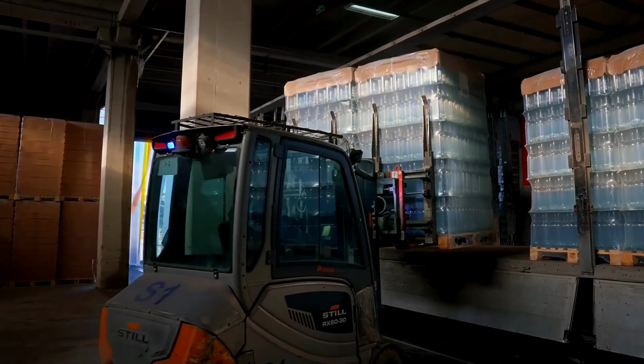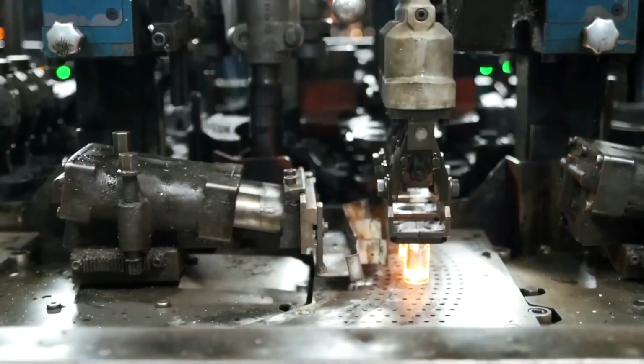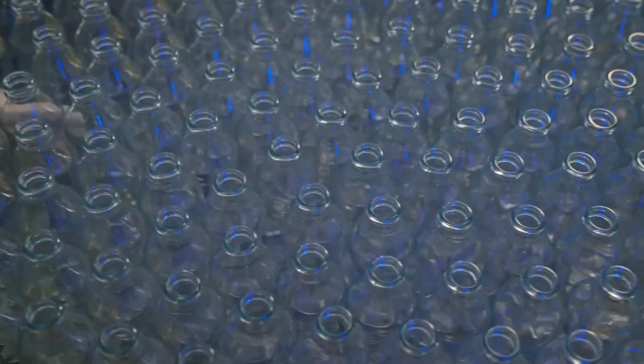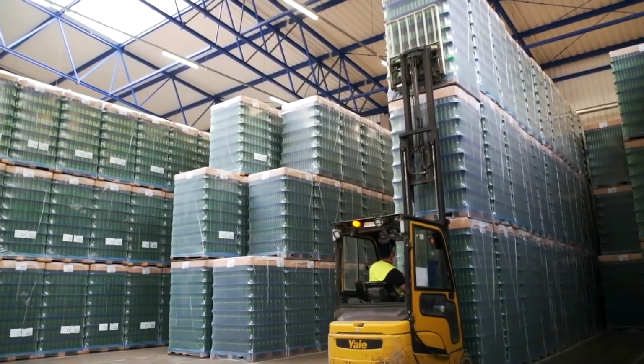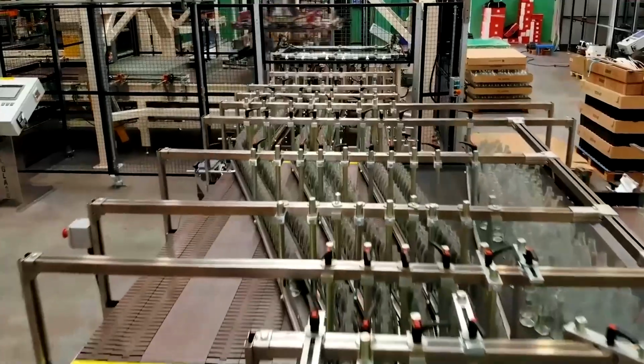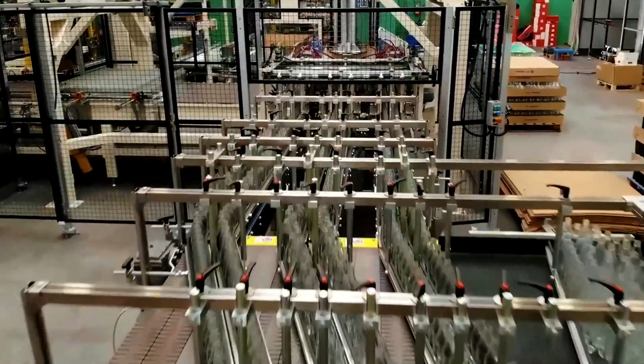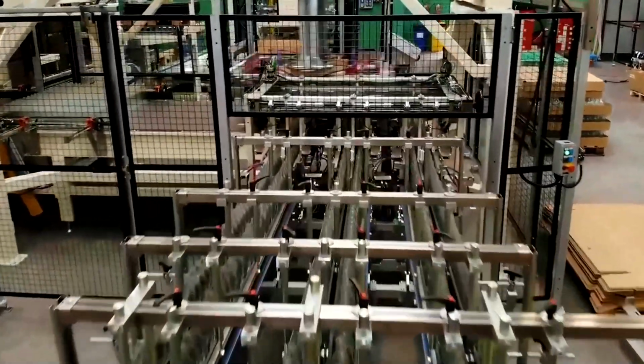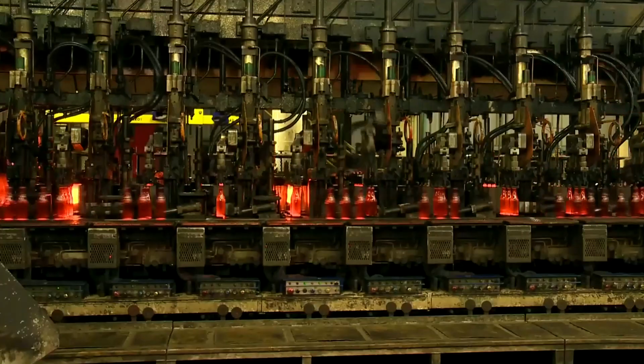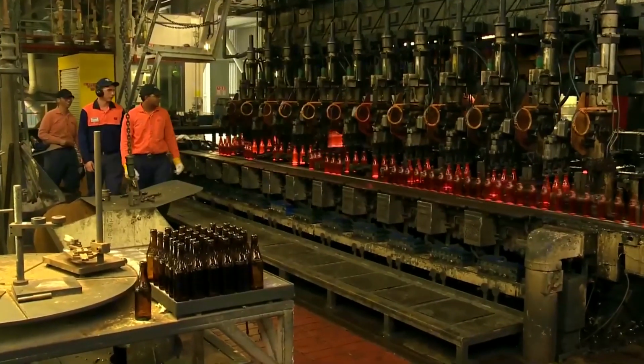Inside the preliminary mold, a powerful jet of compressed air is blown in from above, pushing the hot glass outward against the metal walls. This action forms the initial shape known as a parison, which resembles a hollow, bubble-like structure with a narrow neck. Still glowing with intense thermal energy, the glass is gently transferred to the final mold, located just a few inches away on the same production line.